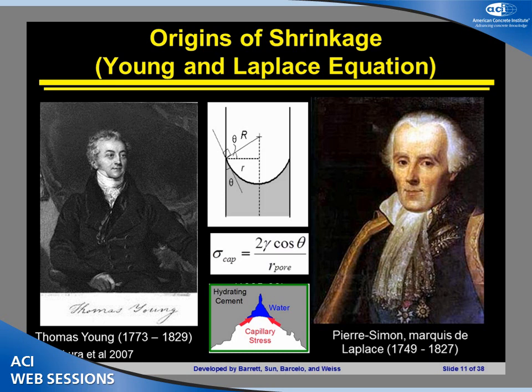And really the idea here is we can relate the stresses that develop inside of the capillary fluid to the surface tension of the fluid, a contact angle, and the size of the pores that start coming up inside of the system. So we're going to keep coming back to this idea because what I'm going to talk about is really fundamentally rooted in this equation right here, where if we understand the pore size distribution and we understand how we're modifying the pores and what size pores we're modifying, we can get a direct implication on what we're doing to the shrinkage of the system.